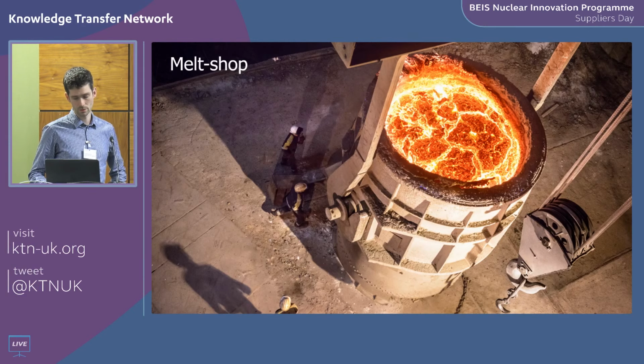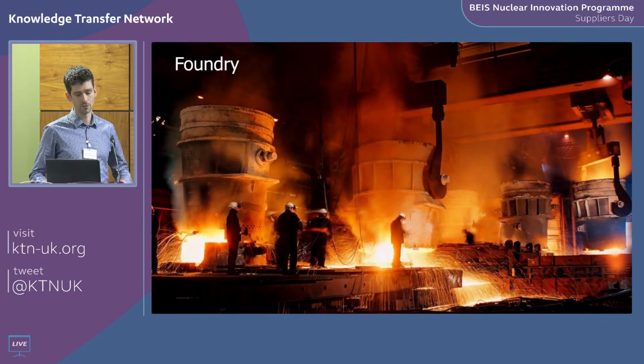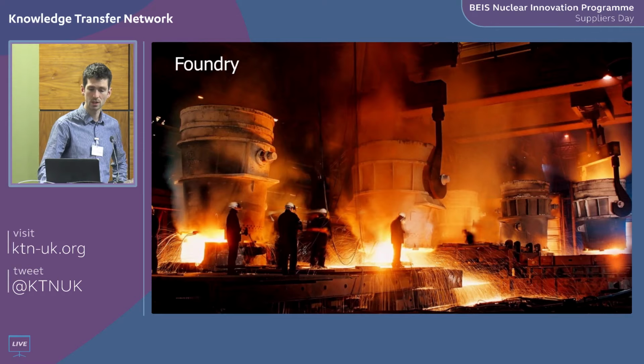With that liquid steel, we're able to send multiple ladles over to our foundry, where we can form sand casting in pits. Our current record is a 700-ton liquid steel pour of the largest casting we have currently made. Or we can take that liquid steel and pour it into an ingot mould and allow it to solidify.